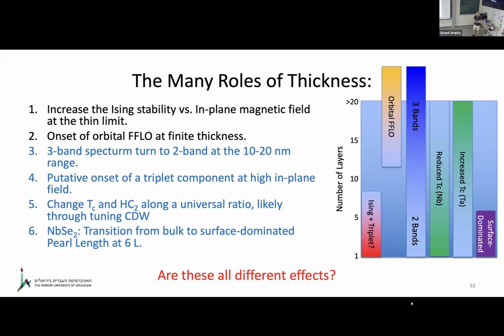The reason is, I didn't want to go too much into the technical details. If you try to fit Dynes model BCS, it simply doesn't work for these materials. If you try to fit anisotropy, it doesn't work. It's a bit of an Occam's razor: the more parameters you add, the better your fit is going to be, because you just have more tuning parameters. McMillan is a plausible model which works very well. It could be working well because it has no free parameters, but it works very, very well. And I think Tristan, you also showed data which looked very much like ours and also fit very well.